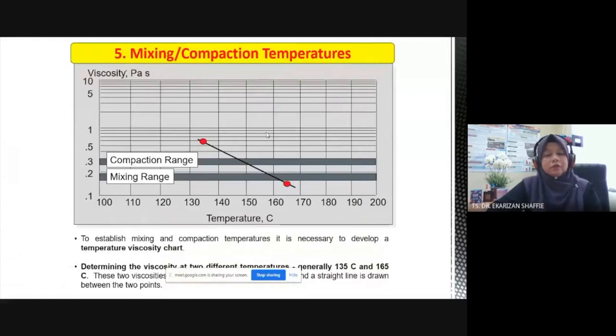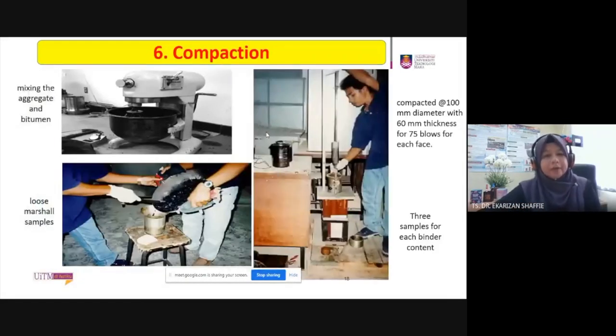Next, in order to mix and compact the sample, we need to conduct a viscosity test. We conduct the viscosity test at 135 and 165 in order to check the mixing temperature and compaction temperature range. For the next step, compaction, we have to mix the aggregate and bitumen. After mixing, we use the loose mixture sample to compact at 100 millimeter diameter with 60 millimeter thickness, 75 blows for each face. Normally, we have to prepare 3 samples for each binder content.